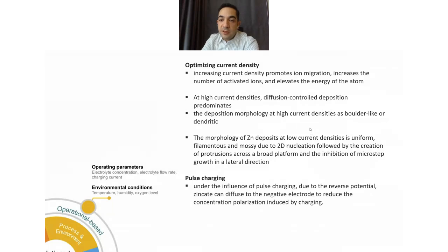The morphology of zinc deposit at low current density is uniform, filamentous, and mossy due to 2D nucleation followed by creation of protrusions across a broad platform and inhibition of microstep growth in a lateral direction. Some literature is also using pulse charging to eliminate issues like dendritic morphology, so that the reverse potential in pulse charging can help the zincate to diffuse back to the negative electrode, and therefore reduce the concentration polarization induced by charging.